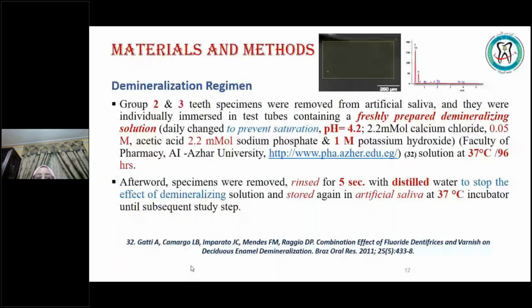Demineralizing regime. The demineralizing regime was done, we know, for group 2 and group 3 before the remineralization stage, and the group 2 and 3 teeth specimens were removed after the artificial salivation and individually immersed again in test tubes containing freshly prepared demineralizing solution, which was changed daily to prevent saturation of the demineralizing solution. The pH of the demineralizing solution, acidic as we know, was 4.2.